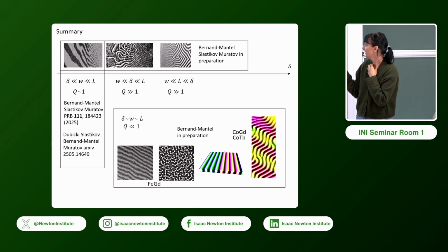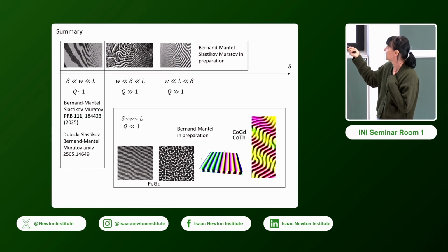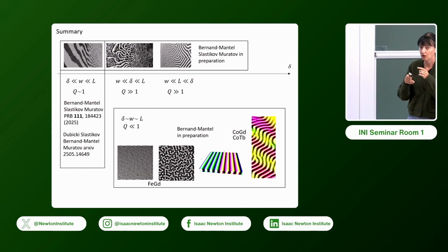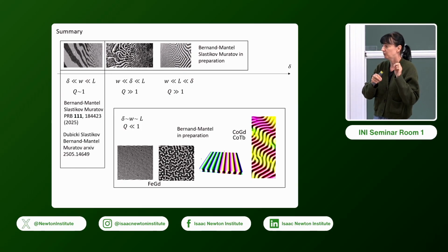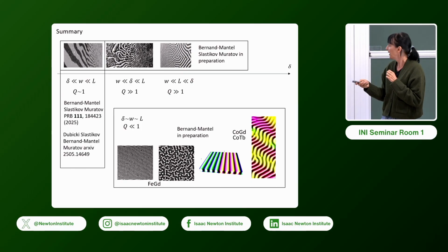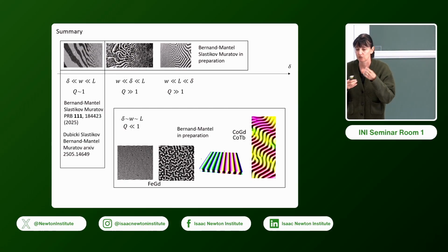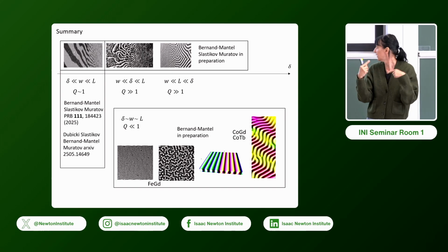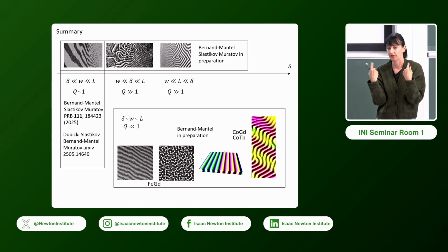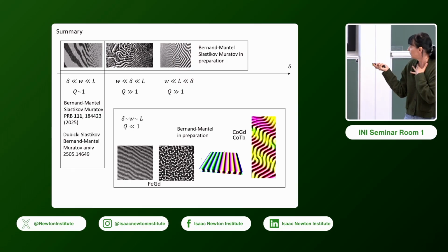And this will have an impact on what you observe, which is not visible here, but can be visible. And also, you now can create this array of bubbles or skyrmions with these two different types. And here you can see an image of such a very dense array where we have some very ordered structure, and we have these skyrmions which can be quantified at plus or minus 1 depending on the rotation of this Bloch core.